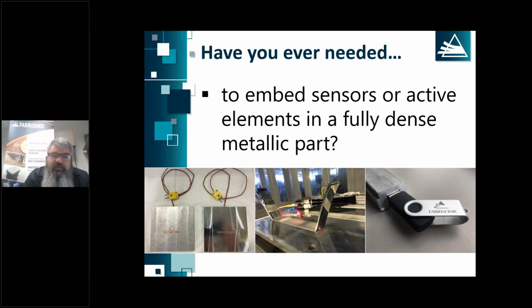That means there's absolutely no melting. In fact, most of the parts that you're going to see throughout the presentation today never got above, say, 200F. So the lowest setting on your oven at home, that's as hot as these parts ever get, and only for a very short time. At any given point in a 3D build, we're only seeing that temperature for, say, 100 to 200 milliseconds as the welding device is rolling over the surface. Because of this low temperature, it allows us to embed pretty much anything in solid metal parts.